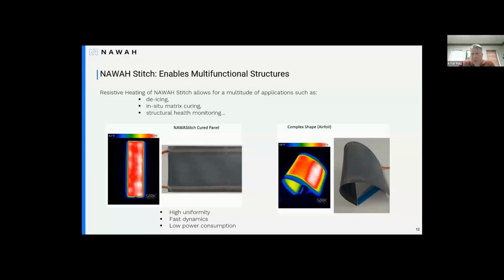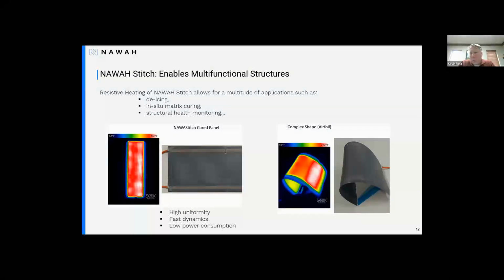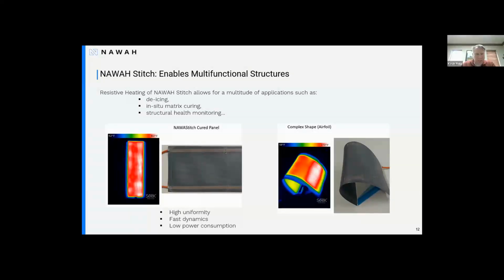The other advantage this gives you, because the thermal conductivity is so uniform throughout the panel, is that you can use it for inspection. As it takes damage, you change the resistance or you change the thermal profile that you see on the part. Therefore, you can help monitor the structure or check it for damage through a resistance check.